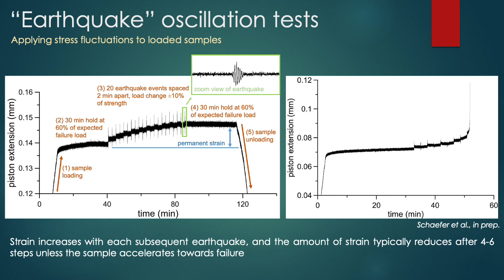On the left, a sample in compression annotated for the different stages of the test. On the right, a sample in tension which failed on the 10th oscillation cycle. In both cases, when the oscillations begin, the strain in the sample increases from the load-hold condition, but in the surviving example, the increase in strain with each subsequent event reduces, whereas in the case where failure occurs, each event causes more and more strain.